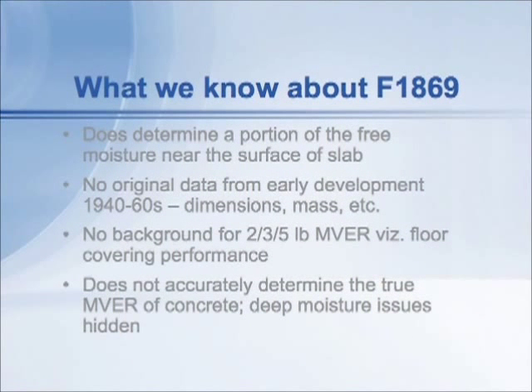In summary, as far as the calcium chloride test ASTM F1869, we know that it does determine a portion of free moisture near the surface of the slab. We know that unfortunately there's no original data, no pedigree to this test from anything that was done in the 1940s, 1950s, or 1960s. The reasons for the dimensions of the kits, the amount of calcium chloride, or even the fact that we use calcium chloride — there's no scientific basis for all that. We don't know of any real technical background for two pounds, three pounds, or even five pounds moisture vapor emission as having been chosen as the limits for installing floor coverings and adhesives going back 30 or 40 years.